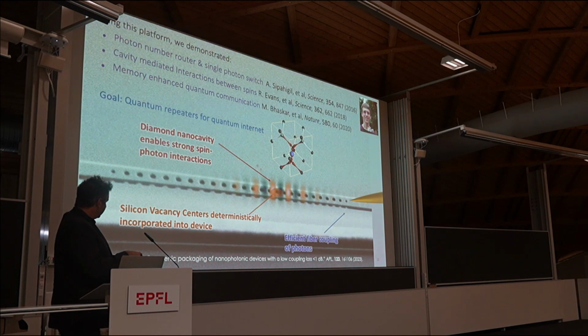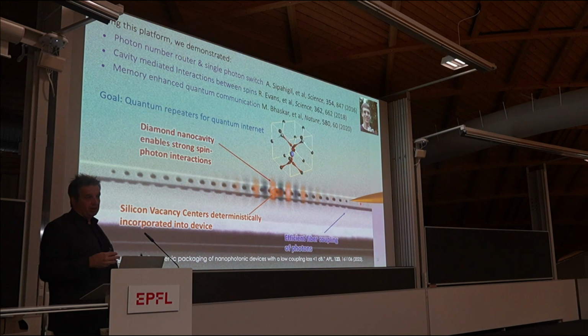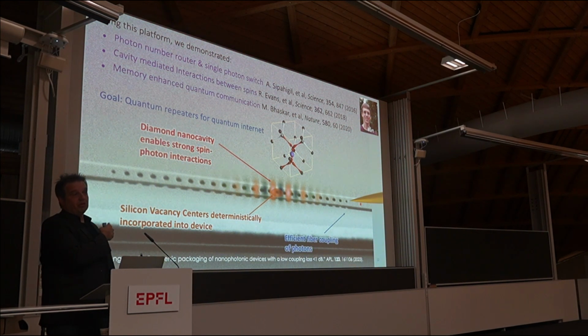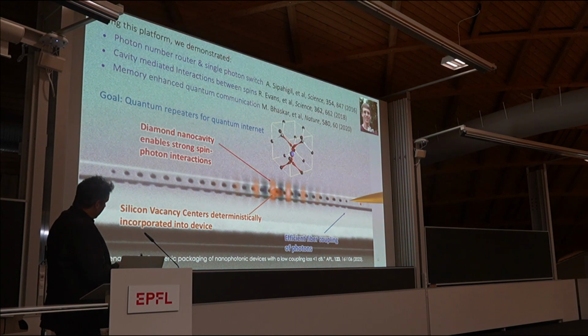And for that, we have developed, in collaboration with Amazon Web Services, who are supporting some of this work, an extremely efficient interface to optical fibers, with efficiency of about 90%. We probably want it to be like 99% eventually, so you don't lose any photons. And by the way, we are now using it mostly for classical communication because it's so good. Using this, we can demonstrate, together with Mikhail Lukin, and I should point out all of this work was done with Mikhail Lukin's group, an important demonstration for the field.